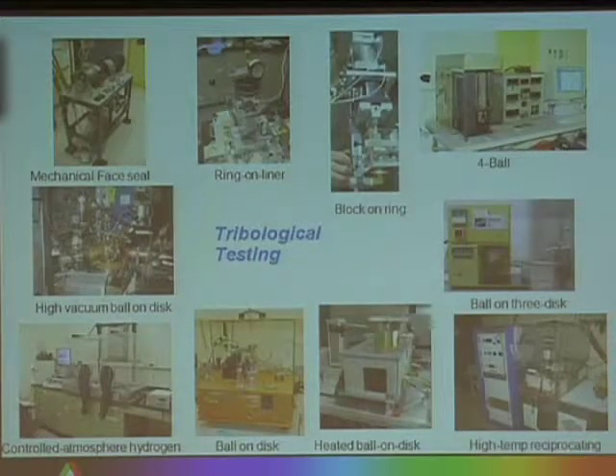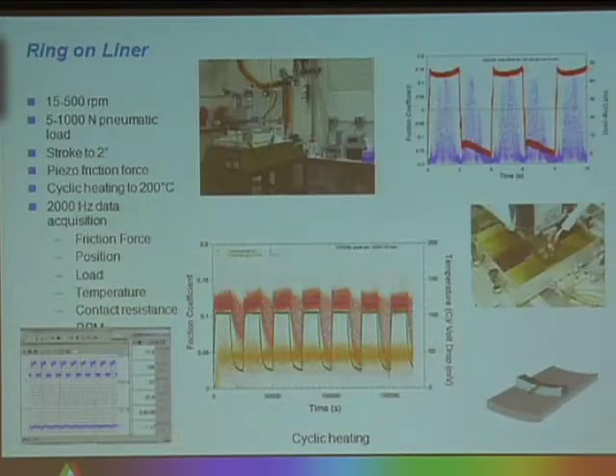You can use various types of oils. You can control the temperature, control the sliding speeds, such that you can get very good conditions that you can model and reproduce. Some of these are four ball, a very high contact stress configuration that's used to look at very high contact stresses with oils, down to a system that we use for testing materials in hydrogen environments. We probably have about 15 different types of test rigs in our group.